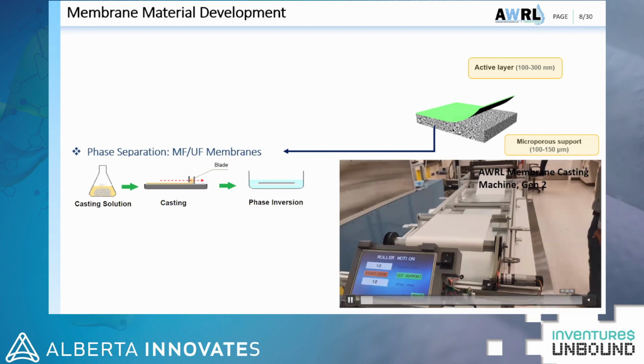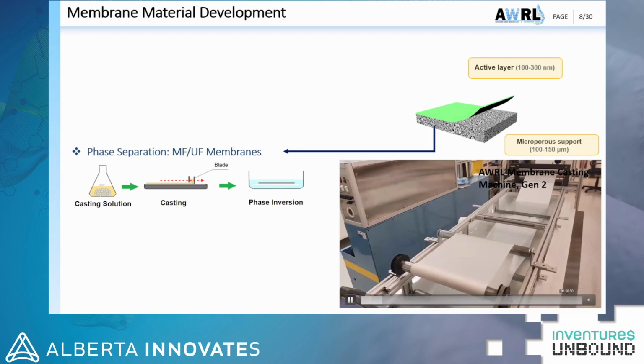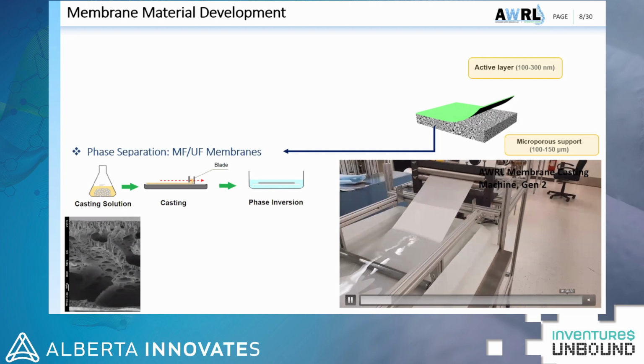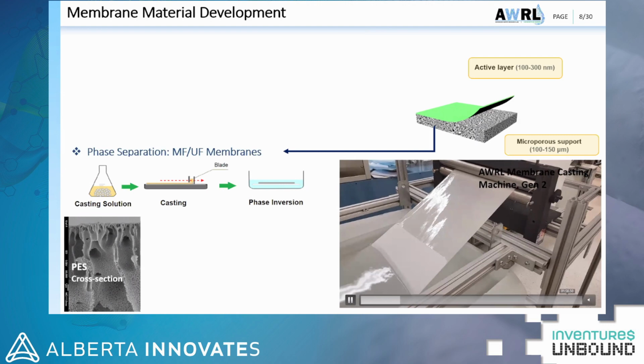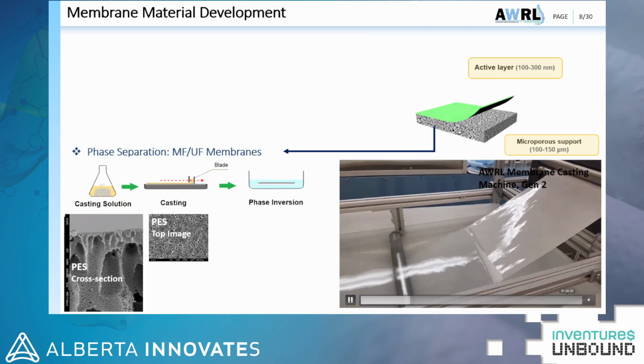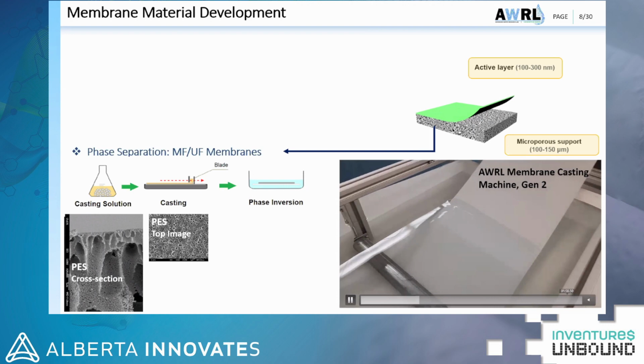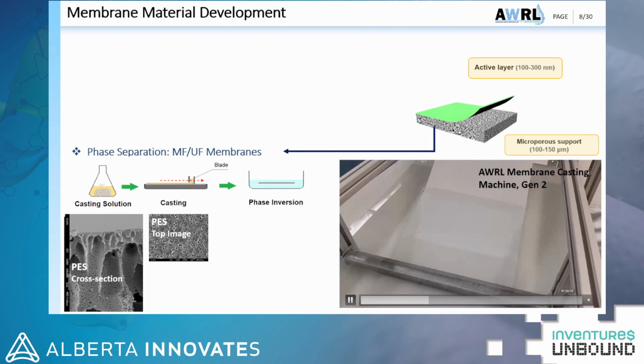You can see here the cross-section image of the phase inversion membrane, and it is an asymmetric membrane. The top layer is dense and the bottom layer has microvoids in it. And this membrane again has an asymmetric structure with a denser skin layer and more porous sublayer. And the top microscopy image of these MF and UF membranes shows that we have visible pores on top of these membranes.